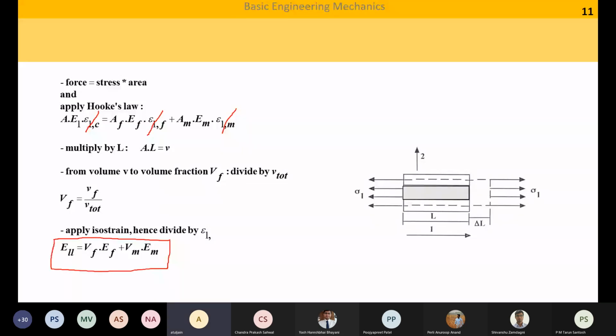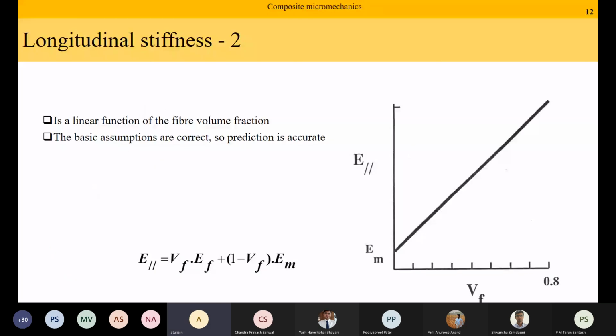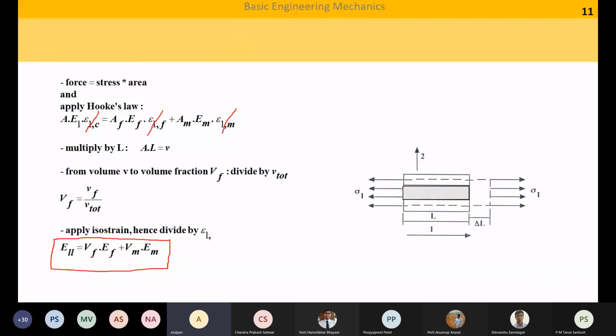That the Young's modulus of the composite in the longitudinal direction is the volume weighted average of the properties of the fiber and the matrix. Which means that as I increase the fiber content, the modulus is going to increase linearly. Since the isostrain assumption, the basic assumption that we have made, is more or less reasonable, using this simple formula you can calculate the longitudinal modulus of composites in a very accurate manner. Okay, good. Any questions about this derivation or about this effective property calculation?